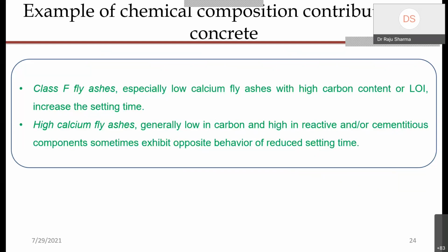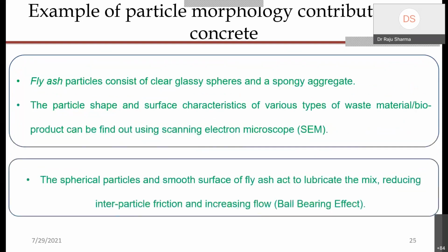So high calcium fly ash is generally low in carbon and high in reactive cementitious components, and sometimes exhibits the opposite behavior of reduced setting time. Okay, so this is the difference. Then fly ash particles consist of clear glassy spheres and spongy aggregates. The particle shape and surface characteristics of various types of waste material and byproducts can be found out using morphological tests, such as scanning electron microscopy.